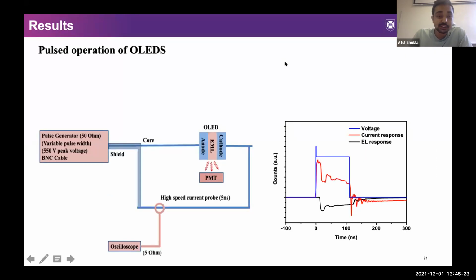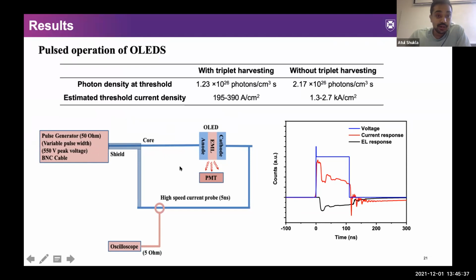So next we wanted to see how far we can go with these devices and how much current we can put in, because lasing requires very high current densities in order to get stimulated emission. So we first used this pulse measurement setup. We had variable pulse generators to inject high current densities, and we detected the signals using the PMT. And then we estimated the current density that would be required to get the singlet population to the ASE threshold.